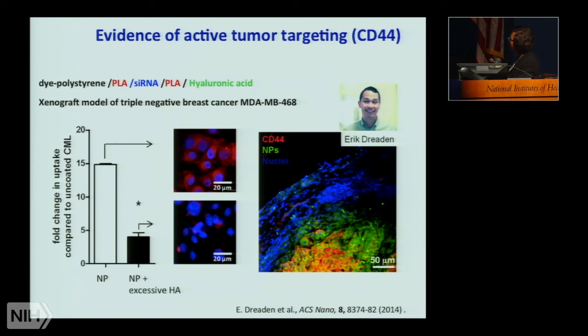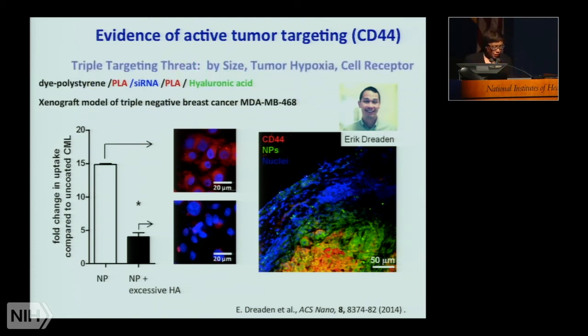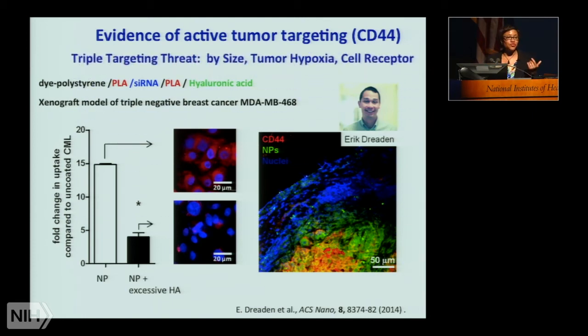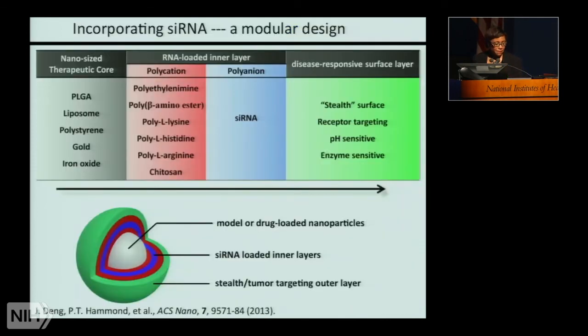When we do a tumor section in this case and label CD44 with red and the nanoparticles with green, again we can see a huge overlap between the localization of our nanoparticles and the localization of the tumor cells. And what we see in this outer region are the stromal cells that surround that tumor, which suggests that we have a mode of triple targeting. We're using nanoparticle size, we're using the tumor microenvironment, or hypoxia, and we're using the cell receptor interaction to ensure that these nanoparticles are taken up.